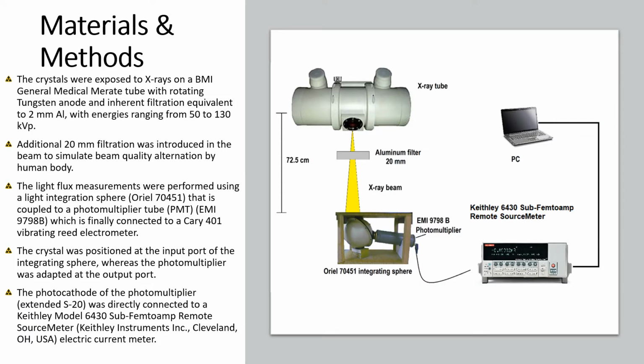The experimental setup used during this study is shown on the schematic diagram on the right. The crystals were exposed to X-rays from a BMI General Medical Merate tube with a rotating tungsten anode and inherent filtration equivalent to 2 mm aluminum, with energies ranging from 50 to 130 kVp. Additional 20 mm filtration was introduced in the beam to simulate beam quality alteration by the human body. The light flux measurements were performed using a light integrating sphere coupled to a photomultiplier tube, which is finally connected to a vibrating reed electrometer.